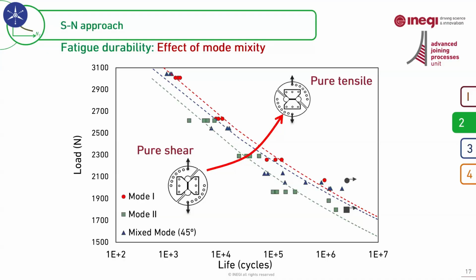In several tests that we have performed on many different types of adhesives, we have obtained a consistent finding, which is a higher fatigue life for pure mode 1 than pure mode 2. It means that if the joints are subjected to a pure mode 1 loading condition under cyclic loading, they can provide a much longer fatigue life than pure mode 2, sometimes by a factor of 10 or even more. It means that if a joint subjected to pure mode 1 lasts for 10 years, the same joint under pure mode 2 under the same fatigue load will last only 1 year. So that's the huge difference between the life for mode 1 compared to mode 2.